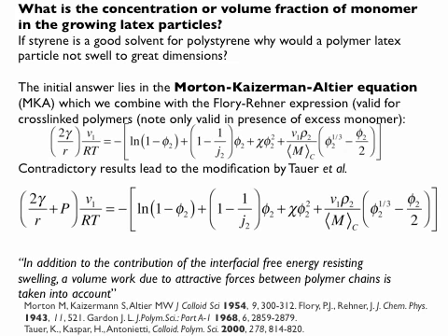Yeah. So the underlying question now is, why does this not happen in the case of particles? And so that's something people looked at. And the initial answer lies in the Morton, Kaizerman and Altier equation, the MKA equation, which is combined with another equation, the Flory-Rehner expression, and the total of that is displayed in this large function under there. But now we have to digest this function a little bit. Yeah. So let's first look at the right-hand side of this equation.